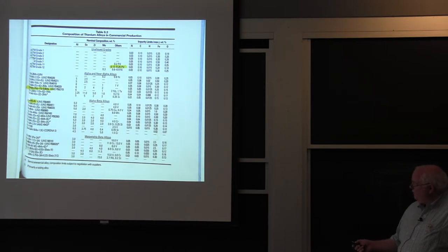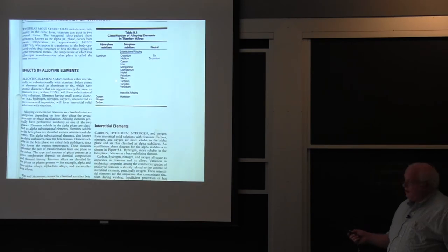There's titanium-6-4. I'll talk about the 6-4 type alloy in a little bit, but it was developed over here at Watertown Arsenal in about 1945 or 47, when titanium first started to become available in larger quantities. There is this alloy, titanium-6211. Six aluminum, two niobium, one tantalum, and 0.8 moly, and they call it TI-6211. That is the U.S. Navy TI-100, 100 KSI strength material. Has no other application that I know of other than the Navy buys it because they did a lot of work at David Taylor to prove it out as the Navy's choice of strength, toughness, weldability, et cetera, back in the 1960s or so.